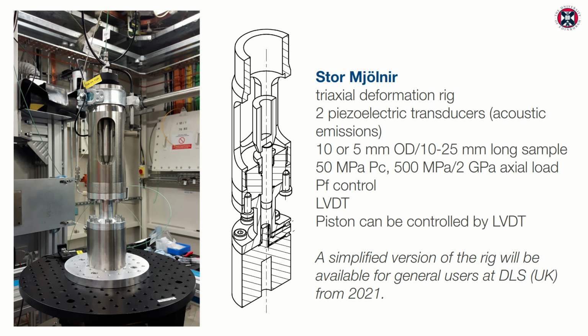Another very exciting rig that we built, well, essentially last year is Stor Mjolnir. Stor Mjolnir, that's Mjolnir obviously being Thor's hammer. Stor Mjolnir is the large hammer. This is a big brother of the cell that I just showed you. This is another triaxial deformation rig, which not only has the advantage that it takes larger samples. Here we can pack in 10 millimeter OD, 25 millimeter long samples, but it also is equipped with 2 piezoelectric transducers to record acoustic emissions from the sample in an active and passive mode, by the way.